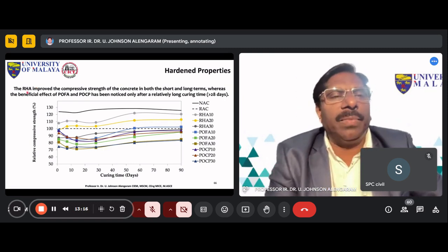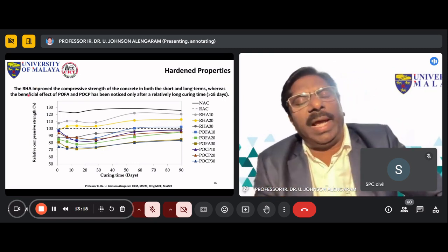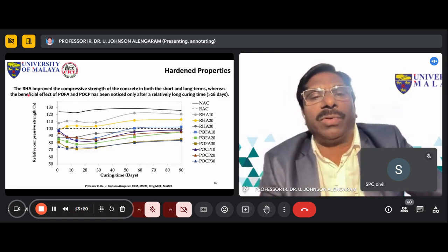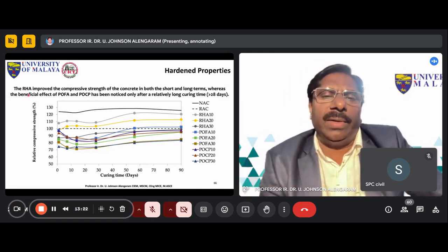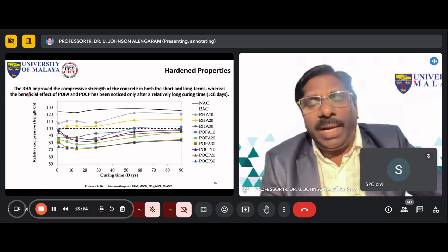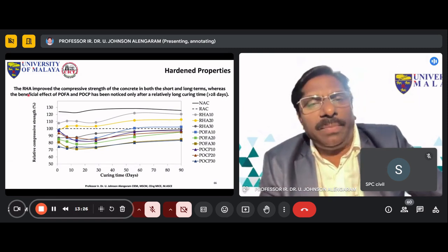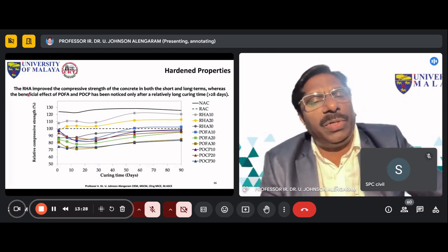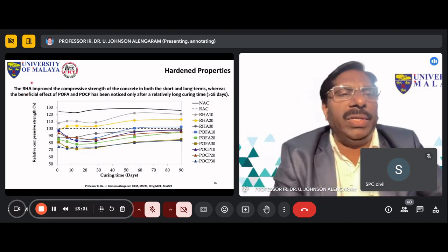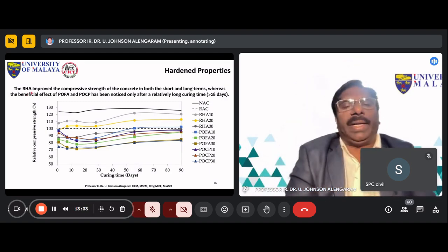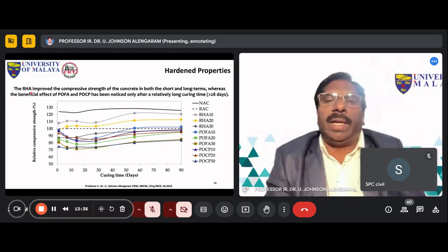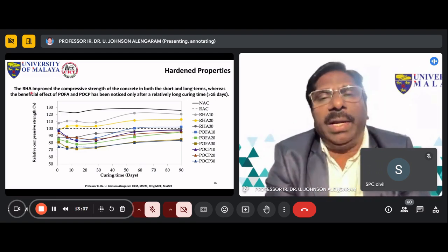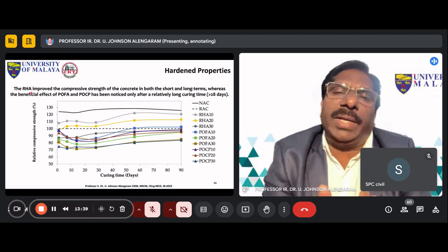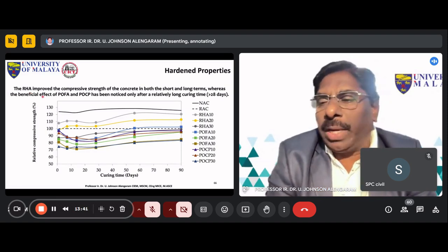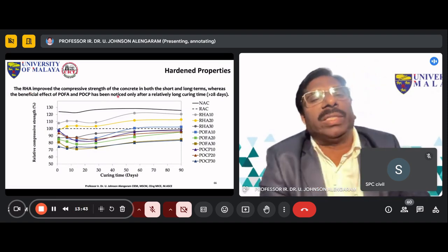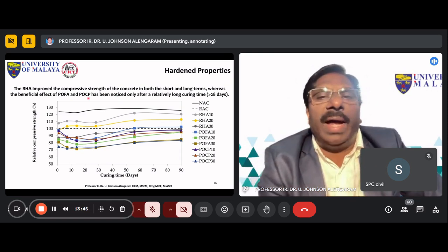But when we add rice husk ash, which has 80 to 90% silicon dioxide, that silicon dioxide can react with the calcium hydroxide, which is a passenger that does nothing towards the strength contribution. Thereby, this RHA, with its silica content or silicon dioxide content, reacts with the calcium hydroxide and produces more calcium silicate hydrate. Thereby, you can get more strength in the concrete. That's what we have done.